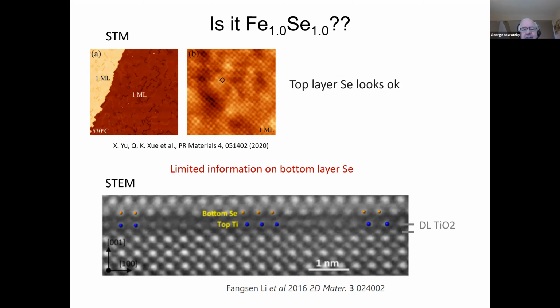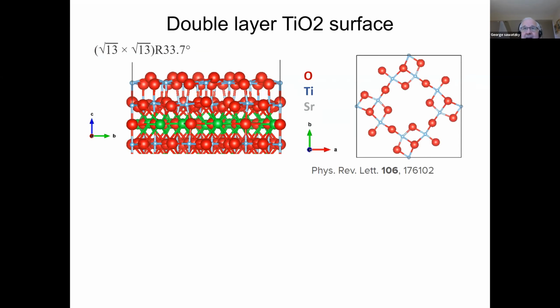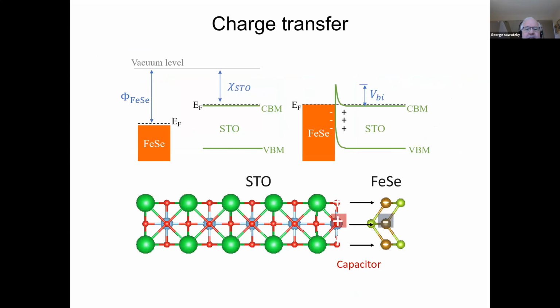although it has a very interesting effect. If you do the density functional and LSDA calculation, you find G-type antiferromagnetic order, so not stripy. That doesn't mean that it's not stripy, but the lowest energy is not stripy in this calculation. But you find that the two moments up and down are not equal. So now you have time reversal symmetry breaking. So be careful. You now have a dipole and time reversal symmetry breaking. I wonder if that really happens, but we don't really know. I'm going to skip this part because I'm running way out of time.